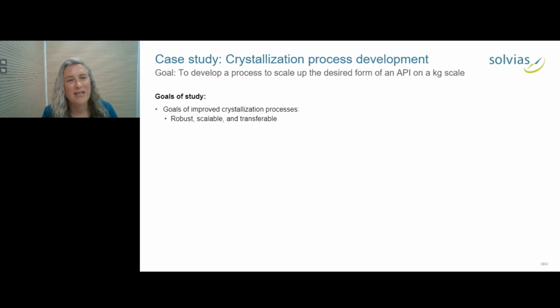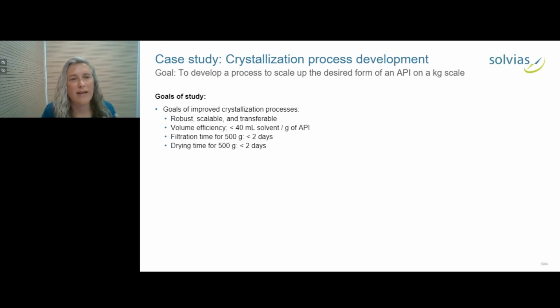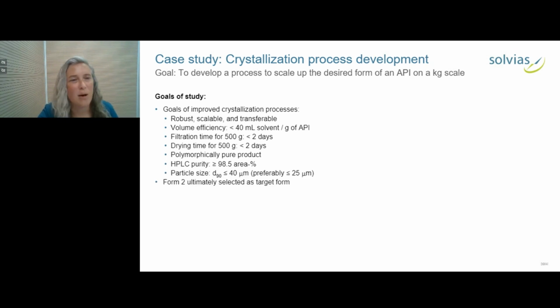And they wanted crystallization processes that were robust and scalable and transferable. They wanted a volume efficiency of less than 40 volumes. That might not seem so stringent. A lot of times 10 is a more common goal, but they wanted better than what they currently had. They also wanted shorter filtration and drying times. Again, these seem like very unusually long times, but they were using solvents with very low vapor pressure, this surfactant and polyethylene glycol, so they basically wanted a significant improvement over their current process. They wanted polymorphic control and chemical purity and small particle sizes.